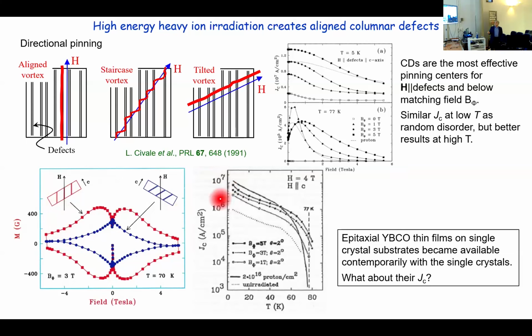So these columnar defects produce similar pinning to random particles at low temperatures and low fields, but they are much better off at high temperature, because they confine the whole core of the vortex.